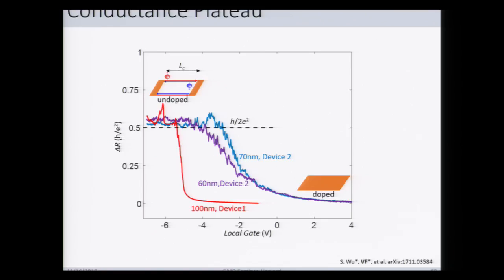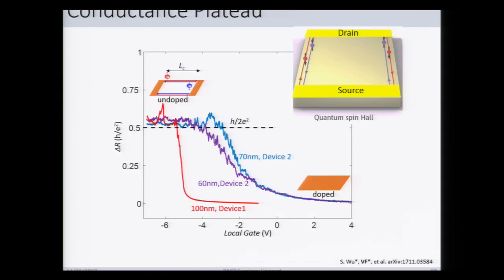This is the change in resistance as a function of this local gate voltage for 3 different local gates of different dimensions on 2 different devices. So again, we start out here where we have a fully doped system, and as we deplete, we get this approximate plateau at slightly higher than half the quantum of resistance. And the way we understand the factor of 2 here is, again, the fact that we have 2 edge modes, and when you apply a bias from your source to your drain, you have a single mode on each side, so a total of 2, giving us h/2e squared.